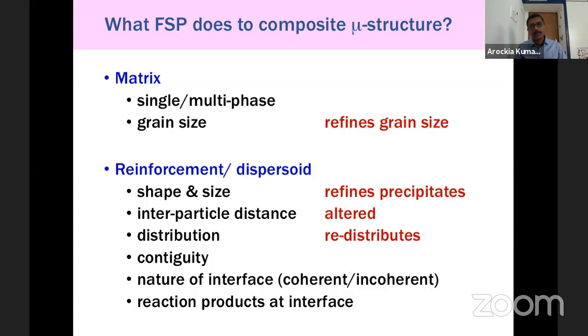Okay, so when it comes to matrix, of course the matrix may have a definite grain size. After FSP, the grain size reduces. And when it comes to reinforcement, you may have a very coarse precipitate or coarse reinforcement before FSP, but these precipitates are refined or broken down by FSP. And the interparticle distance is altered after FSP. And then how it is distributed, previously it may be inhomogeneously distributed, but after doing FSP you may get a very uniform distribution, or vice versa. Contiguity, the nature of the interface, and reaction products can all be altered after FSP. All these things will definitely influence the properties, so we have to keep that in mind.